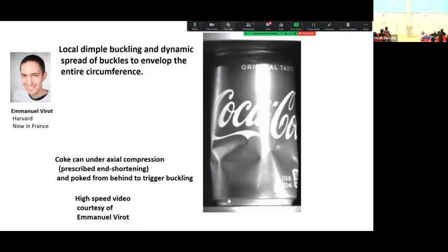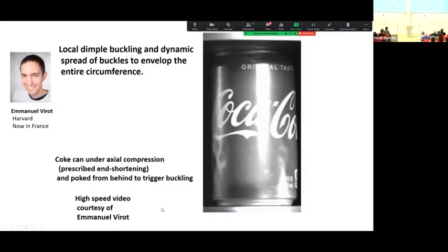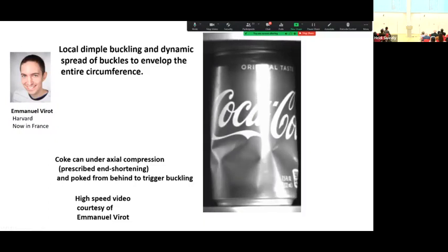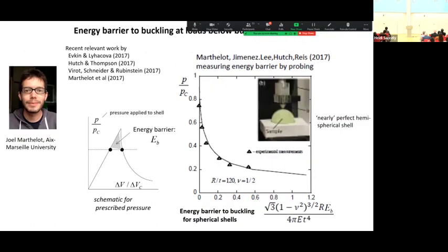And so it is a localized mode. I'll play it once more, but you can see in the very beginning, you see these short wavelength modes, and then they expand to the longer wavelength modes. So it's a very dynamic process. And that's not easy to analyze dynamically, although you can. Some people can. Okay, I'll make this quick. This is very nice experimental work by Joel Marthelot.